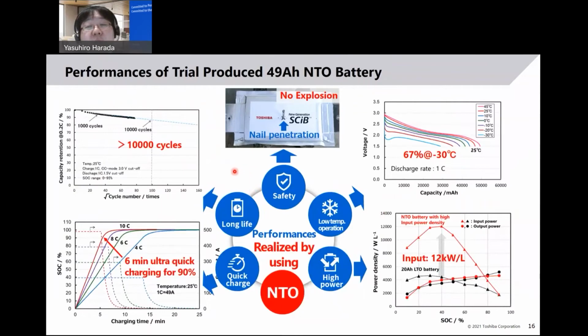This slide shows a summary of a trial-produced 49 ampere-hour battery. This battery achieved almost 50% larger capacity compared to commercial SCIB having LTO. Nevertheless, we can also achieve safety, no explosion even after nail penetration, and long life, more than 10,000 cycles, and 6 minutes ultra-quick charging up to 90%, low temperature usability, even at minus 30 degrees Celsius, and high input power, more than 12 kilowatt per liter, which is much higher than SCIB.